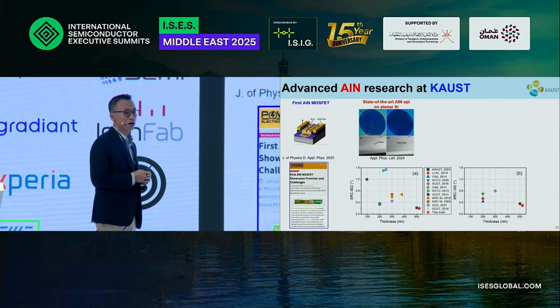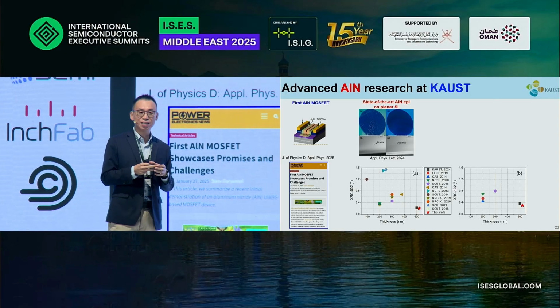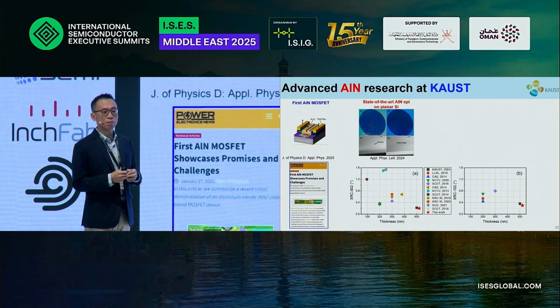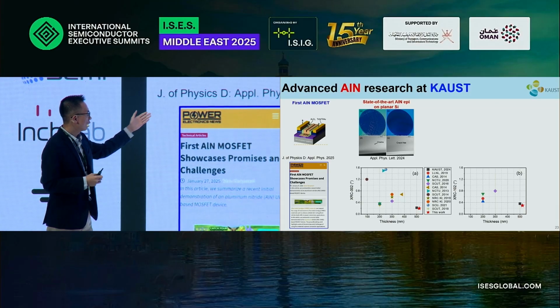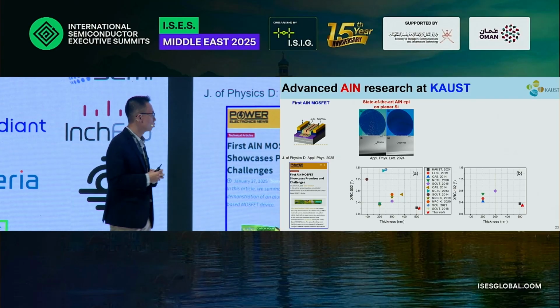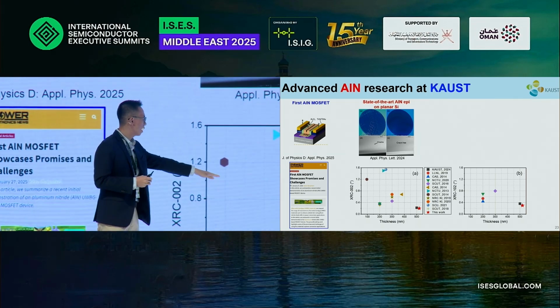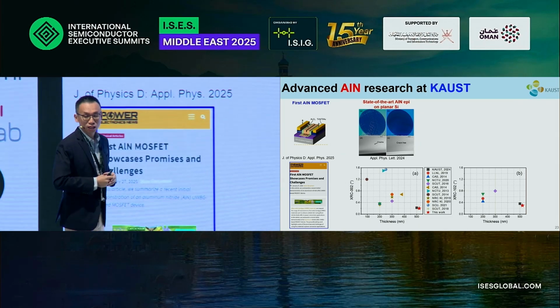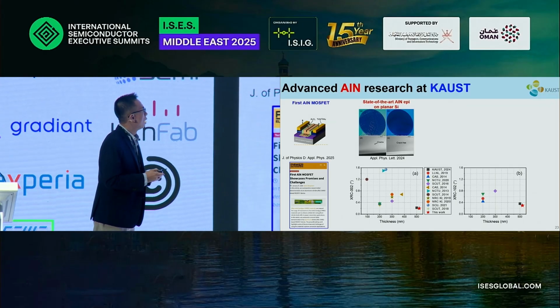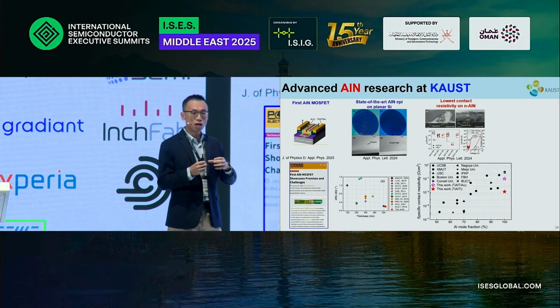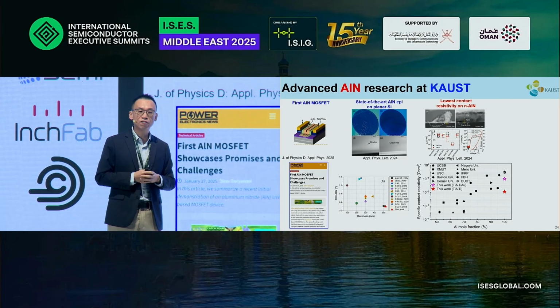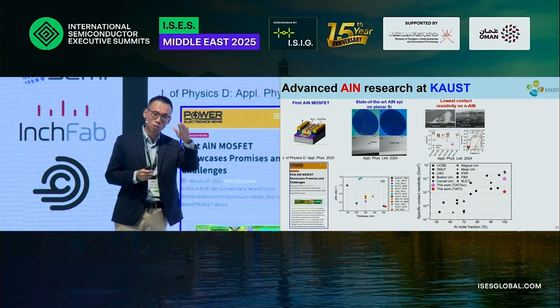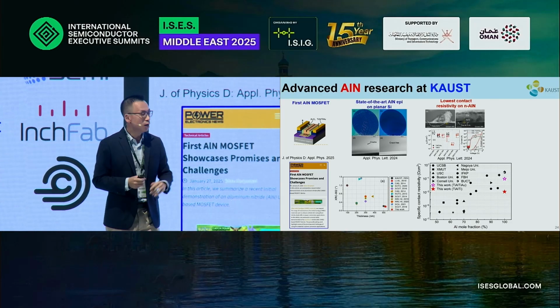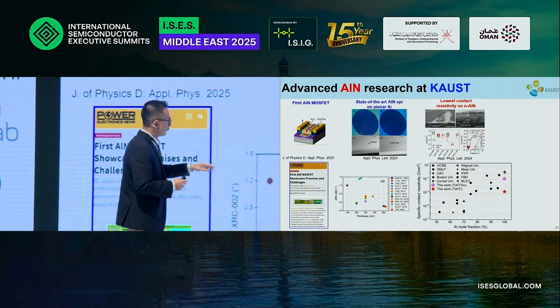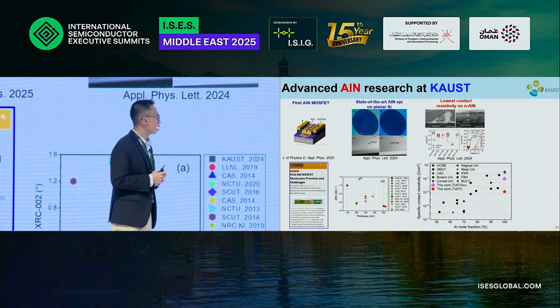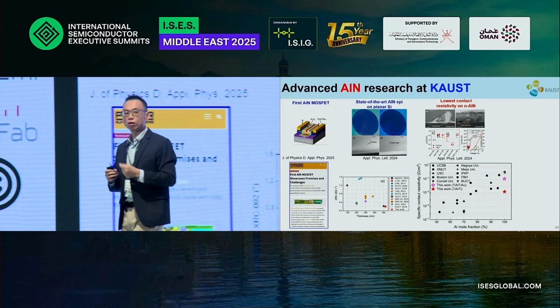Another work that we do at KAUST is that we have a good epitaxy facility on silicon, because GaN on silicon is now becoming a very important technology. We are also actively developing aluminum nitride on silicon. So far, on planar silicon, we have realized the best quality compared to reports by other universities and research institutions. Another work is that when you develop aluminum nitride-based power and RF devices, the contact resistance is very important. You want to bring down the contact resistance as much as possible, as that is related to the overall efficiency. Recently, we have achieved the lowest contact resistivity on pure aluminum nitride.